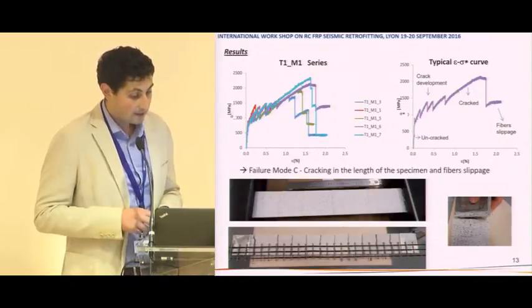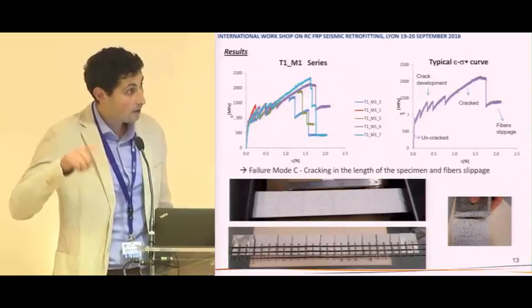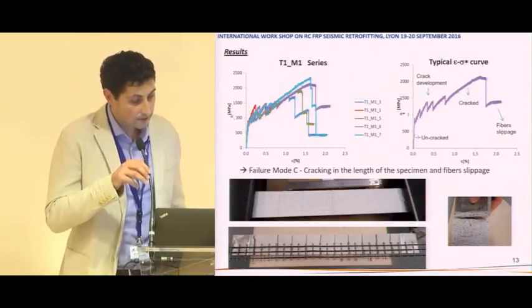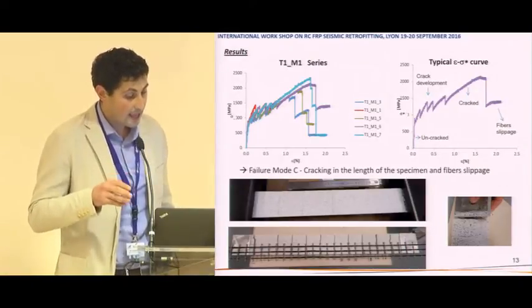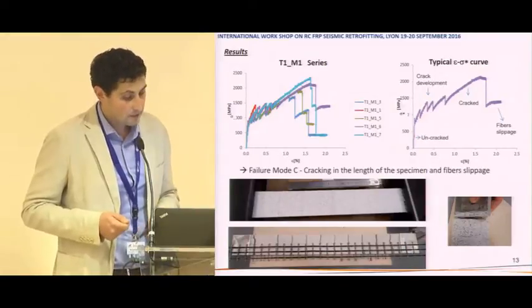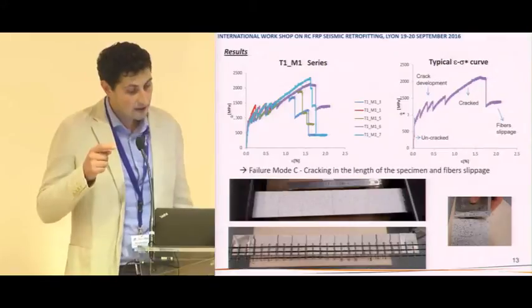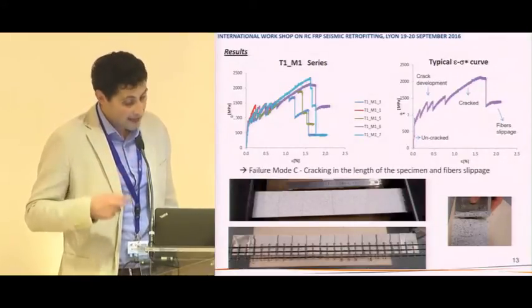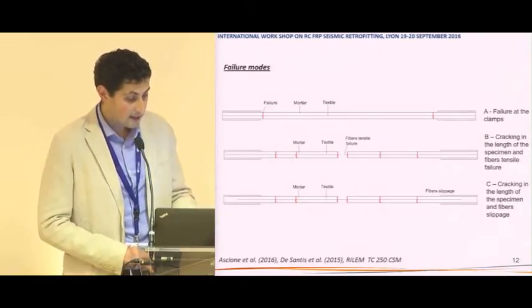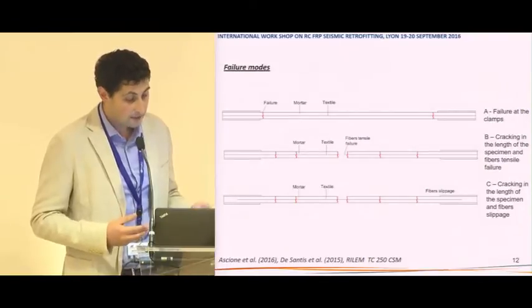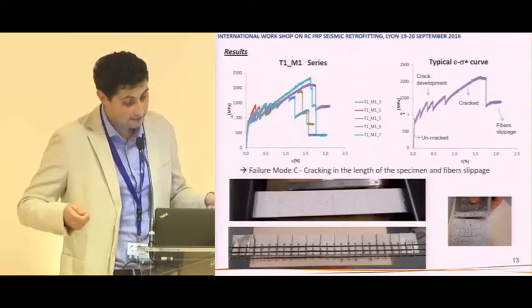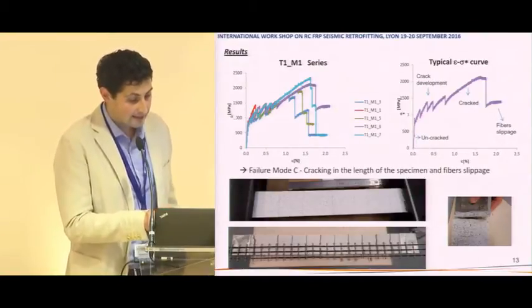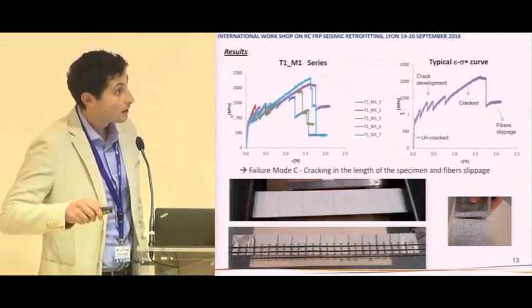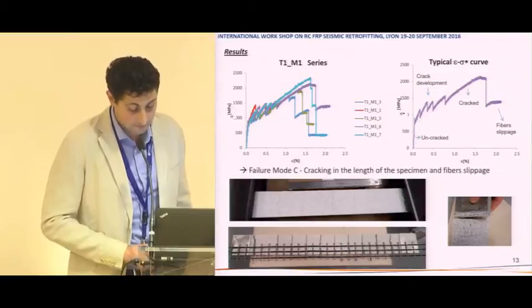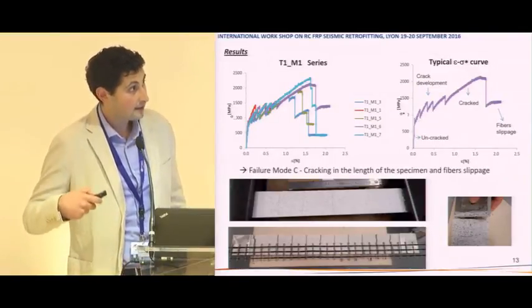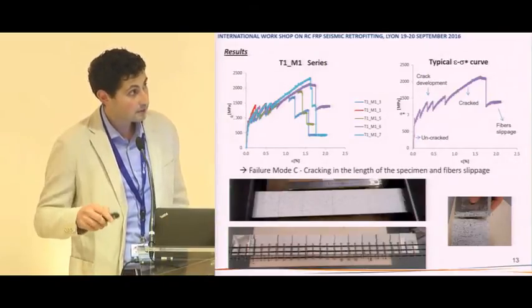When the first crack opens, a sequence of crack openings is recorded. We are in the crack development phase. After that, only the textile works, and we can see in the curve an increment of the stress. In our case, we record failure mode C. We do not achieve the failure of the textile, but a slippage in the clamps. The maximal stress recorded in our test is not the maximal strength of the textile, but the stress related to the start of the slippage.